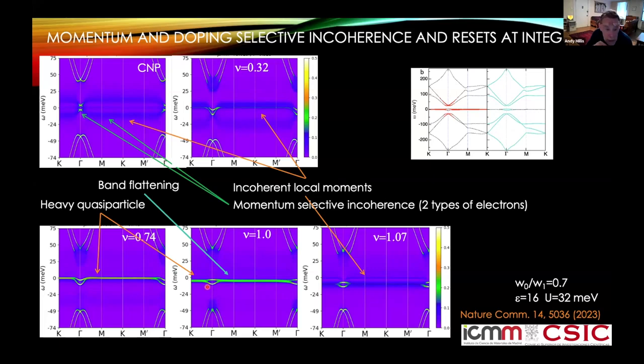I'm asking because this relates to the vexed question of the double counting correction in the whole DFT plus DMFT theory more broadly. What the double counting correction really does is position the correlated bands with respect to the uncorrelated bands. Anyway, thank you very much. That answers my question. That's very interesting.